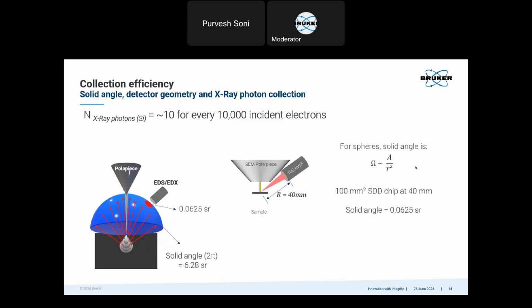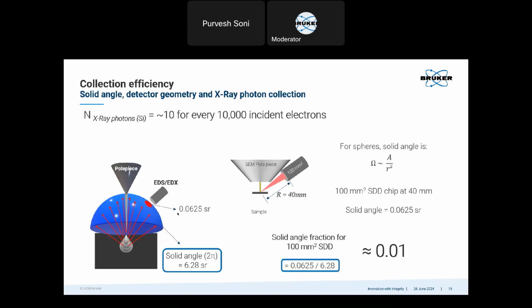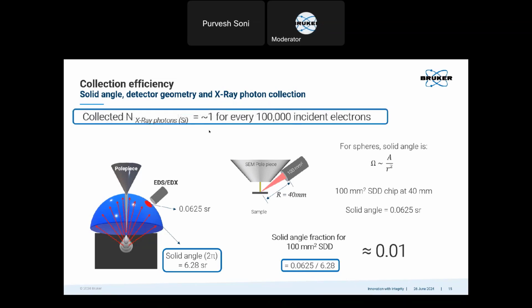And then we use a very simple formula for solid angle. Of course this is not real, the real formula is quite complicated, but for simplicity let's use the basic formula. Then we'll get a solid angle of 0.0625 steradian. If we now calculate the solid angle fraction for this EDS detector over the whole 2 pi solid angle, it will be this divided by this. So it will be 0.01, which means that we will get one X-ray photon collected for every 100,000 incident electrons.